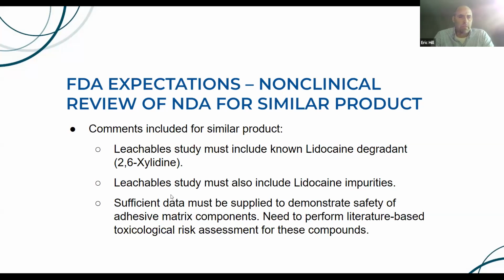And then they directed that sufficient data be supplied to demonstrate safety of the adhesive matrix components. And really what they were looking for there is that they wanted us to perform literature-based tox risk assessments of those compounds. So again, we've got this drug and adhesive patch product, and the FDA was saying they wanted to make sure that we tested sufficiently for not only leachables coming from the backing layer and release liner, but also anything that could follow the drug through the dermal layer during administration from that adhesive matrix.